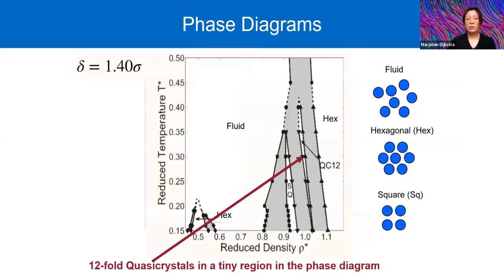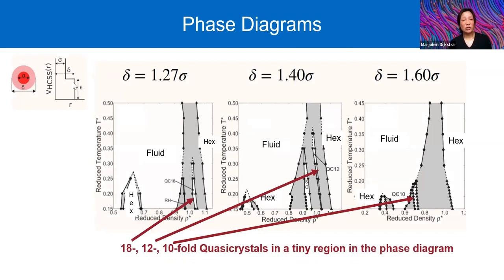And so for this very simple system, we've mapped out the phase diagram already many years ago in a temperature density plane. So this is a two-dimensional system. There's a low density hexagonal phase. There's also a high density hexagonal phase. There's a square lattice. And then in between the square lattice and the hexagonal phase, there's a tiny, tiny density regime where there's a 12-fold quasicrystal. And so it will be really a challenge to find this extremely small density regime where the quasicrystal is stable. We can also change the shoulder width. If we change the shoulder width, we can stabilize an 18-fold, a 12-fold, and a 10-fold quasicrystal.